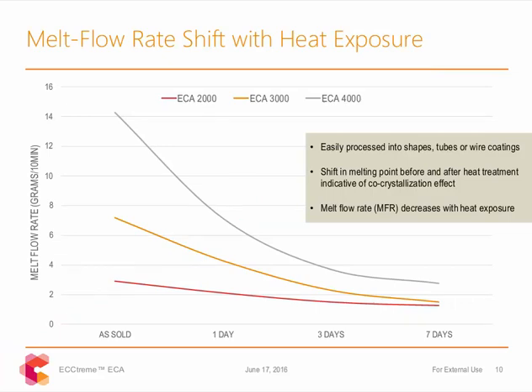Unlike other fluoroplastics, ECA doesn't break down during exposure to extreme heat for extended periods of time. In fact, in some instances, we've observed increased physical property performance after heat exposure. So how do we observe the mechanism behind this increase in performance? We can observe the co-crystallization phenomenon I described earlier by monitoring a drop in melt flow rate after heat exposure. Unexposed ECA, ECA 3000, for example, has an MFR of 7, which will drop to less than 1 following heat exposure. ECA 2000 and 4000 demonstrate similar trends when exposed.